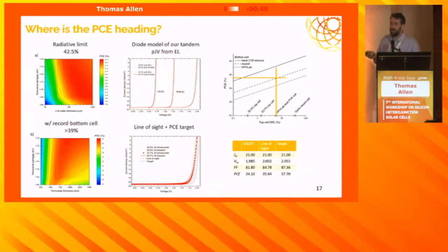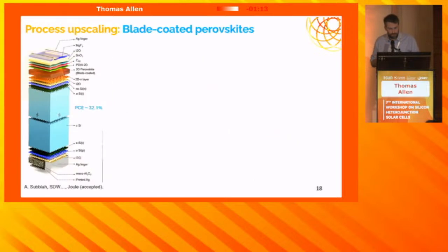But we're still a long way from more narrow bandgap perovskites, so 1.55 eV perovskites. In our lab, this is actually an old result, but that's around 6% radiative efficiency. It's now even higher. But if we were to achieve with the wider bandgap perovskite a 6% radiative efficiency, we can expect something close to 37.5%, we think. That's with the state-of-the-art bottom cell, of course.